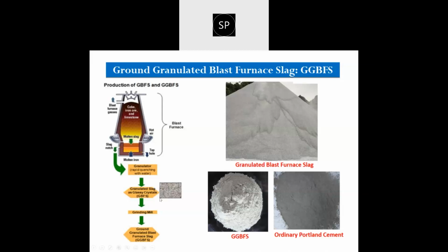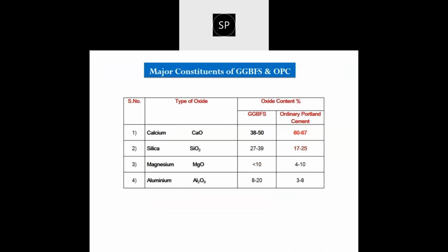Now this granulated slag is ground in a mill, in a dedicated mill, and through this grinding process it gets converted into the ground granulated blast furnace slag, which has a fineness modulus equivalent to cement, and it has very good hydraulic and cementitious properties. With the help of that, we can utilize it as a cementitious binder.